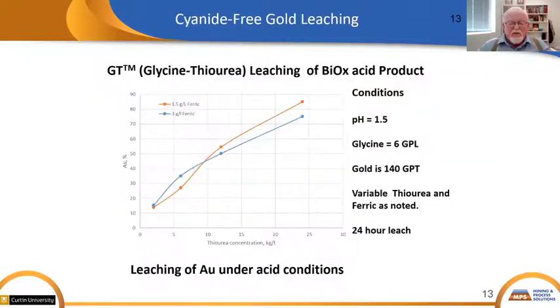Now we also have the GT process, which is a mixture of glycine and thiourea. Here we're leaching gold under acid conditions, pH 1.5. We have gold, it's an oxidized, a bio-ox product, which is very acid. We're leaching it at the pH that it is produced at, 1.5. And we add thiourea, and we see we're getting up into the mid-80s when we add 1.5 grams per liter ferric. And ferric is an oxidant to put the gold into solution.